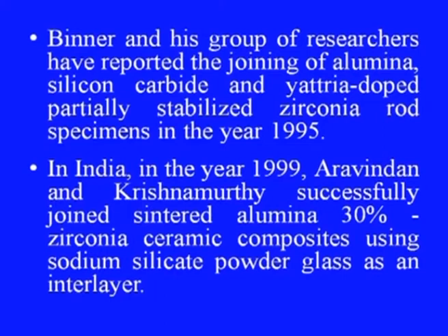In India in the year 1999, Aravindan and Krishnamurthy successfully joined sintered alumina 30% and zirconia ceramics using sodium silicate powder as an interlayer. Then another important development in this microwave joining is microwave joining of bulk metals.